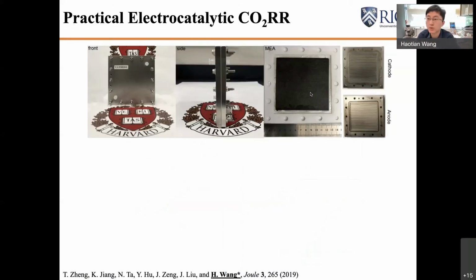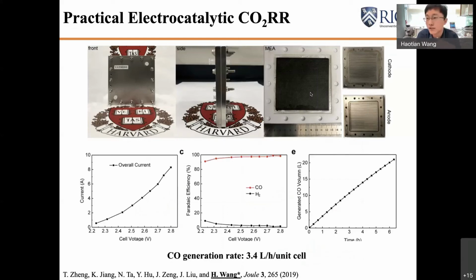And based on that, both the scaling up of the current density as well as the scaling up of the single atom catalyst, we make this MEA cell that is about 10 centimeter by 10 centimeter, that's 100 centimeter square, about this size. And we can now deliver amp scale of CO2 reduction current. And we do the calculation. This is about 3.4 liter per hour CO production rate.